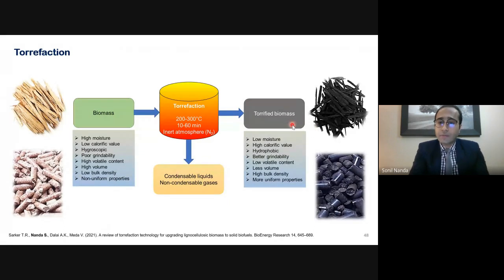Now, when it is torrefied, what exactly happens is, as you can see here, roasting at a temperature of around 200 to 300 degrees Celsius for 10 to 60 minutes, under an inert atmosphere. So the torrefied biomass loses its moisture content. Because it loses its moisture content, the heating value or the calorific value of the biomass increases. It becomes hydrophobic, which means it will generally tend to repel moisture, and it has better grindability. It can be pelletized.